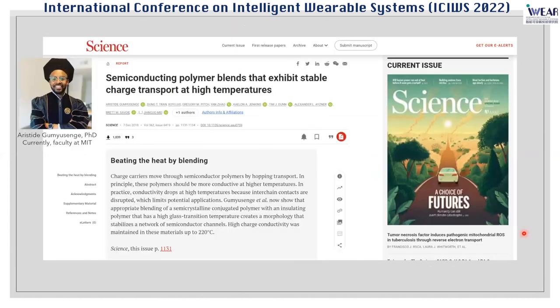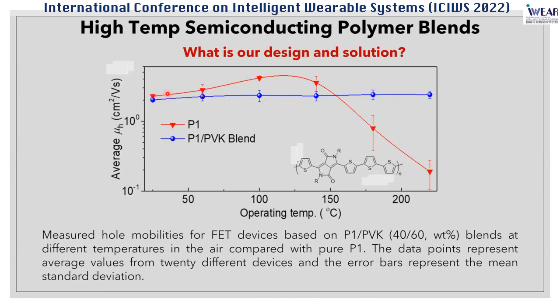In late 2018 and early 2019, we published a paper in which we first demonstrated that semiconductor polymers can perform reliably at elevated temperature. What we essentially did was make polymer blends. For regular semiconducting polymers like a DPP-based polymer — one of the widely studied polymers — as temperature increases, charge carrier mobility increases but then performance starts to degrade. For our polymer blends, they can be stable from room temperature up to 220 degrees Celsius. How did we come up with this design concept?